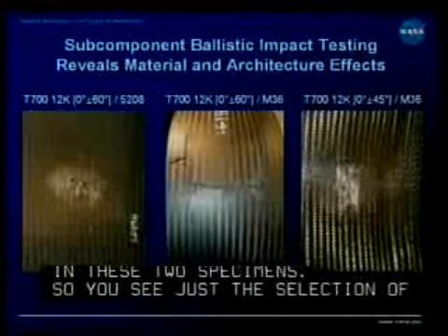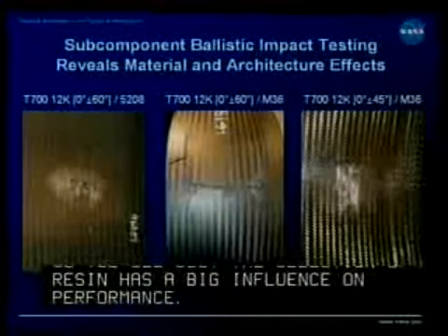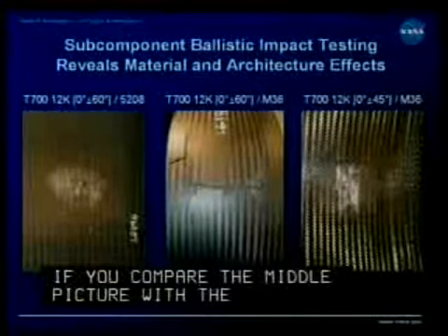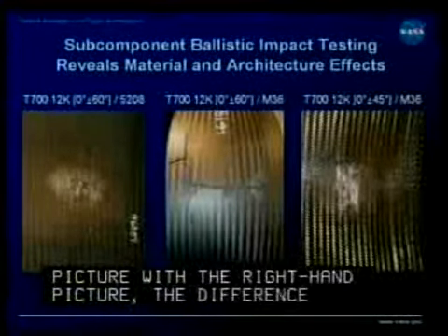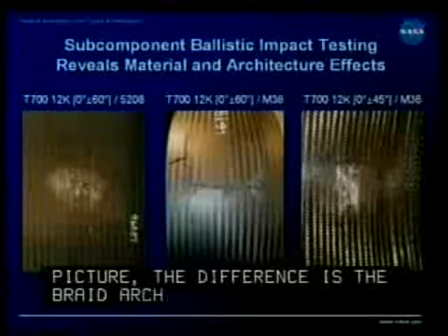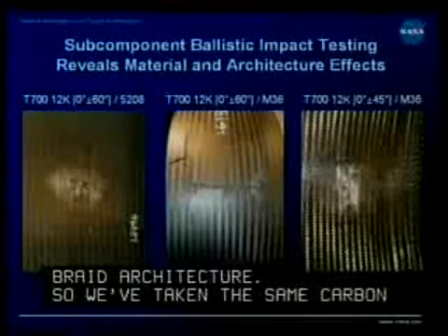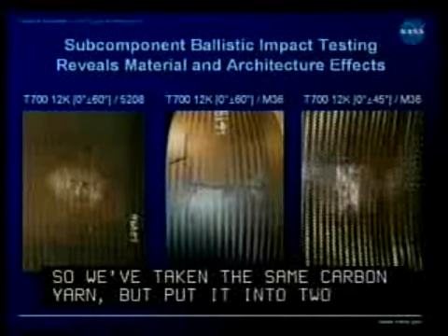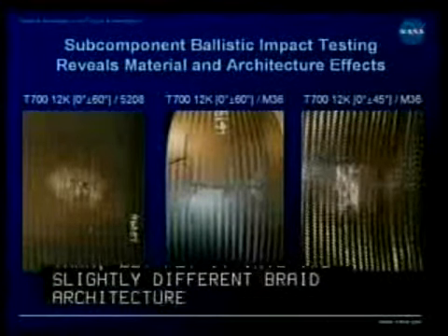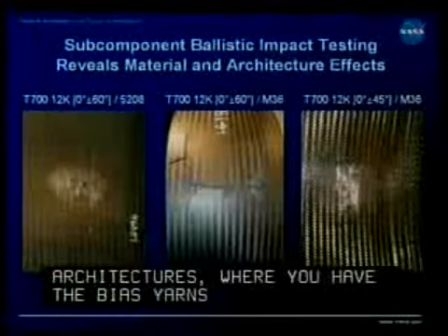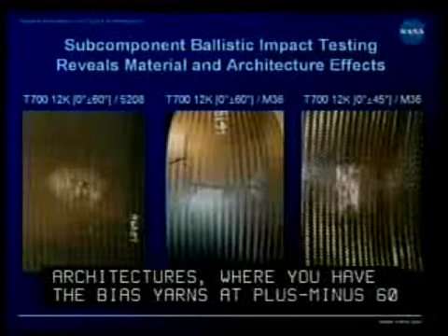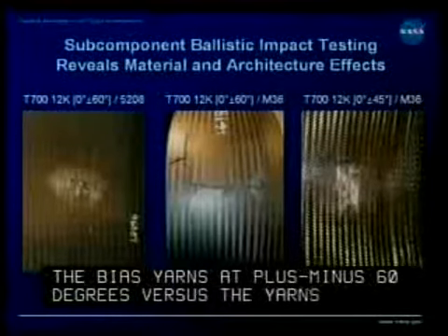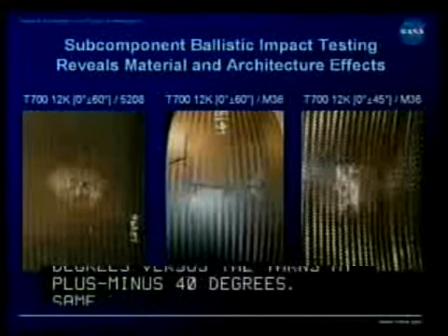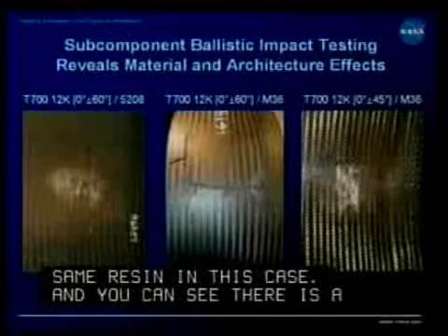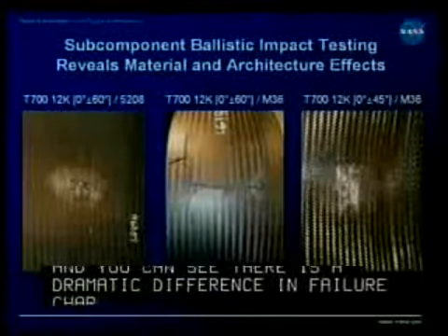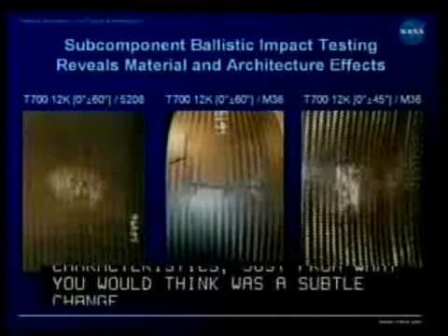If you compare the middle picture with the right-hand picture, the difference is the braid architecture. So we've taken the same carbon yarn but put it into two slightly different braid architectures where you have the bias yarns at plus minus 60 degrees versus the bias yarns at plus minus 45 degrees. Same resin in this case. And again, you can see a very dramatic difference in failure characteristics just from what you would think was a subtle change in the braid architecture. Next slide, please.